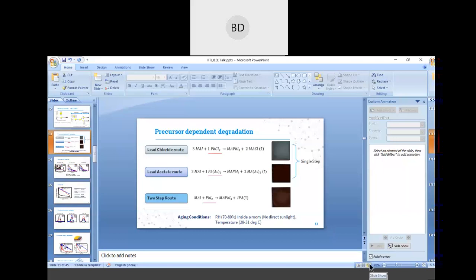But we have not done aging for our precursor solutions. We have done aging only for perovskite films, which is used for degradation. Here, aging means the degradation. Aging means keeping the film outside in the environment so that it has sufficient time so that moisture can attack the film. Thank you. I hope I'm clear, sir.